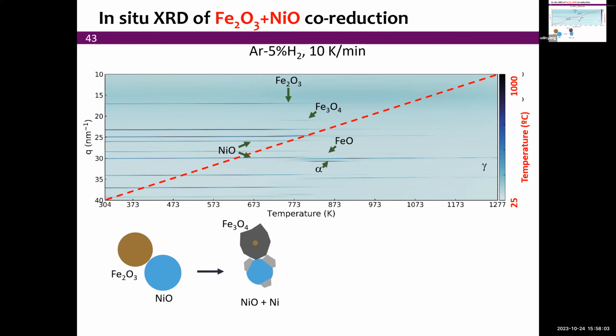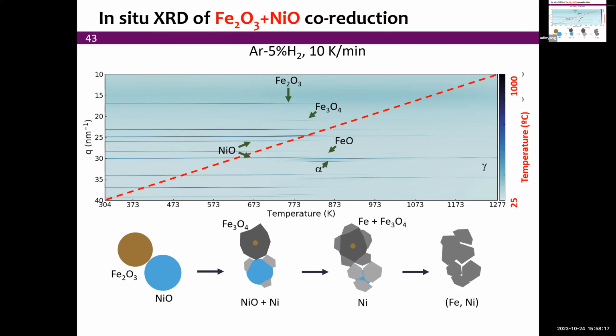So really the story would be that first the nickel oxide is reducing, the iron oxide is slightly behind. It then transforms to a mixture of iron plus those suboxides. Meanwhile, the nickel is almost finished. And then the alpha BCC phase transforms into gamma, which is our final FCC iron nickel alloy that is shown here schematically. So that's interesting because the interdiffusion, as well as the final alloy formation, is happening together with this step reduction between the different oxides.